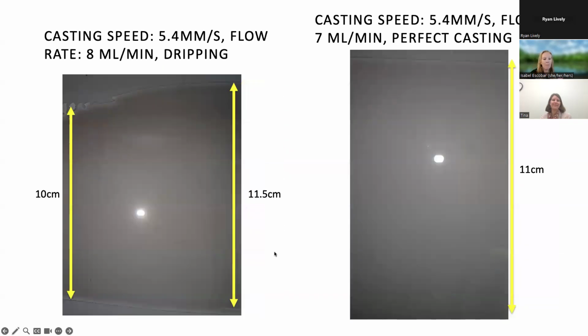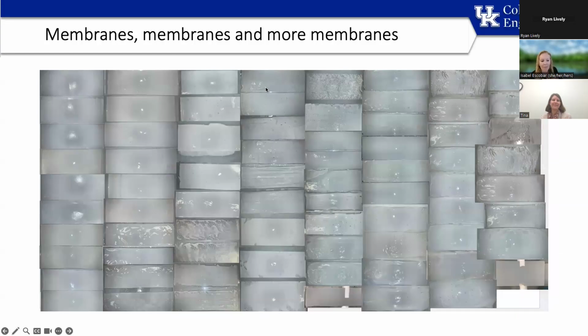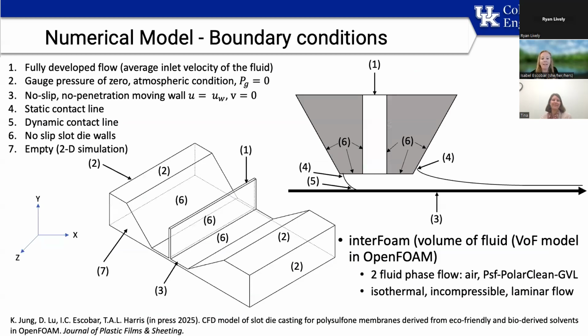And here's an example of dripping, where the membrane is really not forming, and the edges are not uniform. And as my student David loves to show this, we can make dozens, hundreds of bad membranes. We can waste gallons and gallons and gallons of dope solutions in attempting to determine what the casting window is for our green solvents. And any modification that we make, if we went from 17% polysulfone to 18%, we're potentially redoing the entire casting window. So it is labor intensive and is not effective.